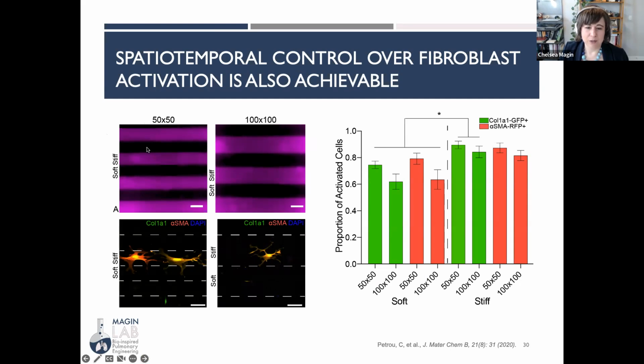So when we look at cellular activation in response to these patterns that we can draw, you can see that 50 microns wasn't quite wide enough to encapsulate an entire cell. So these cells were feeling both soft and stiff microenvironments. But when we got to 100 microns, we could see this cell is all by itself inside a stiff stripe, and it is lit up with both green and red, showing it's very activated. So our results with the proportion of activated cells, you can see there aren't big differences between soft and stiff in the alpha smooth muscle actin readouts, but we're starting to see them in the collagen 1 readouts.